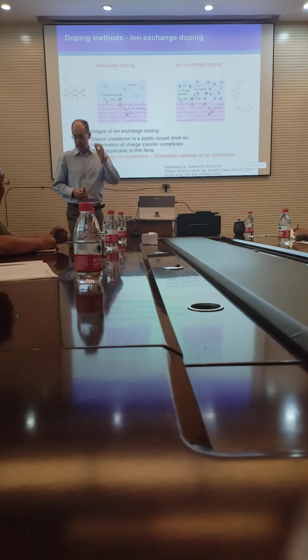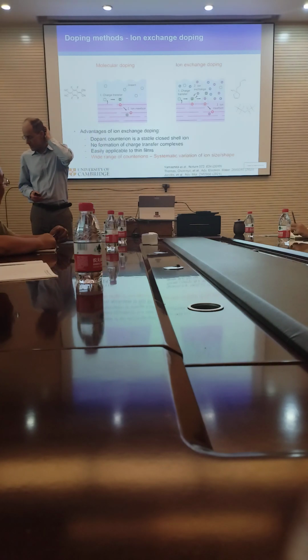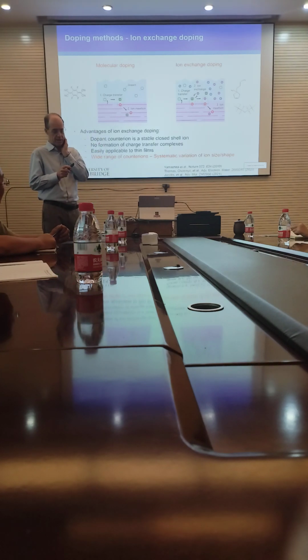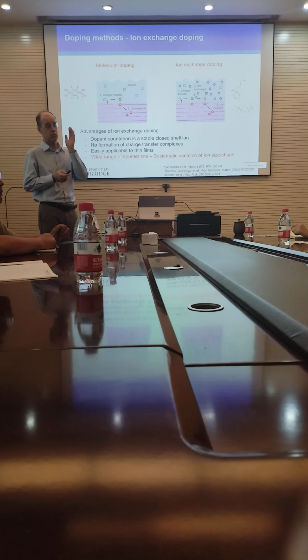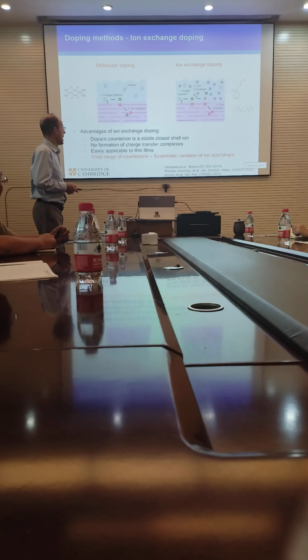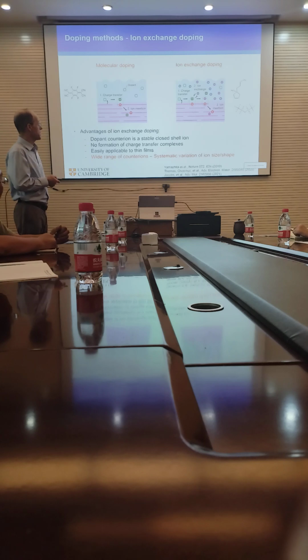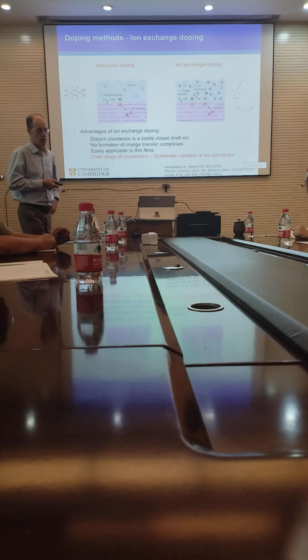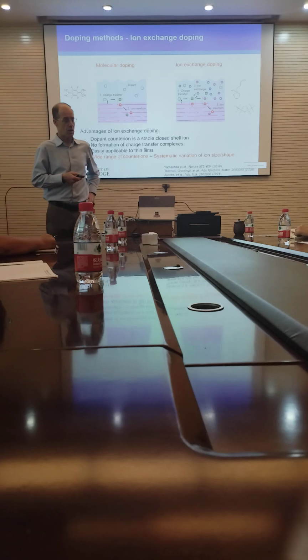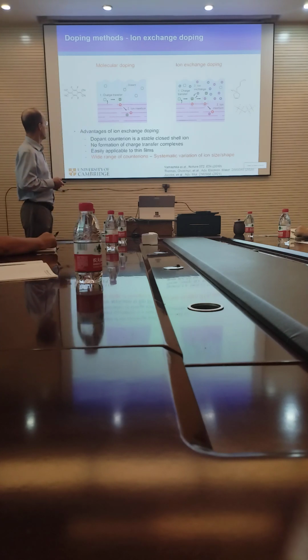So in order to develop these model systems, we had to have some doping techniques that allow you to dope these materials to well-defined carrier concentrations. And we built on some work that was published a couple of years ago by Jun Takeya's group in Tokyo, and developed this ion exchange doping method, which is essentially an improvement over the conventional molecular doping.